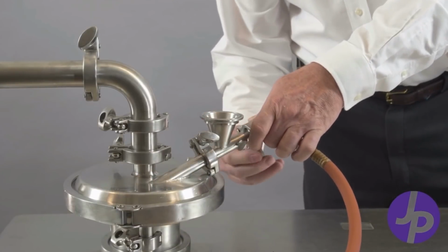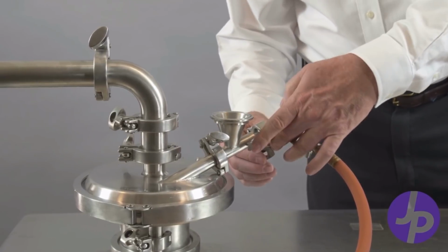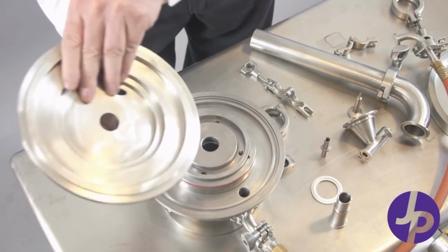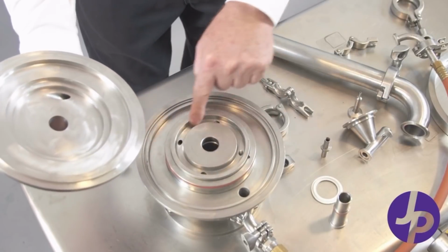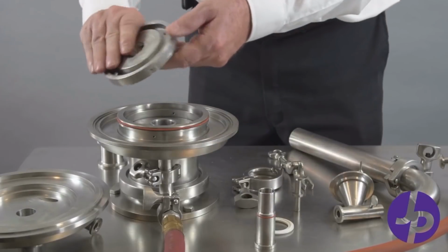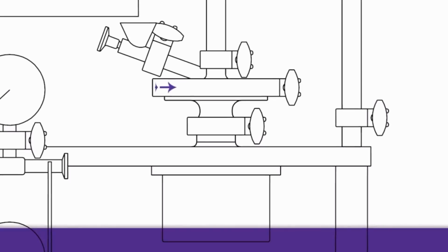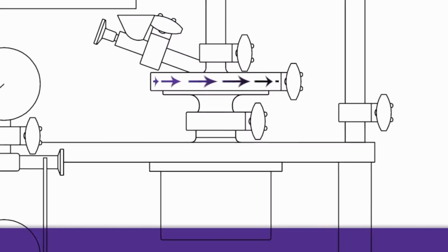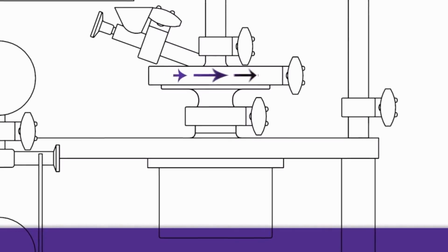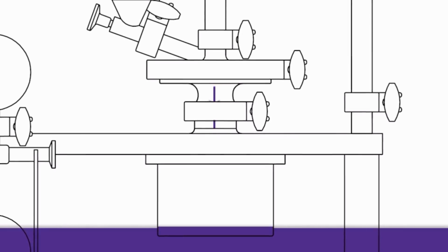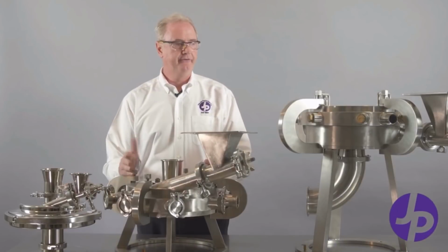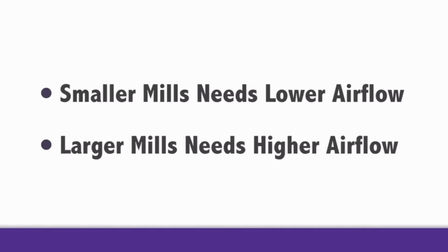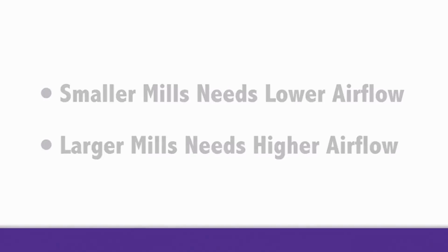So the power source can be nitrogen, it can be air, it can be carbon dioxide. The material is injected into the jet mill. In our case, it goes into the first chamber, which is a distribution chamber. It is evenly distributed and goes through multiple ports in front of the grinding jets. The material goes to the grinding chamber, it goes out into orbit. It stays in orbit and collides with other particles of the same material. As soon as they're fine enough, they migrate towards the center of the mill, climb over a weir, and they're air classified as they come out. Each mill requires a different flow of motive gas. The smaller the mill, the smaller the airflow. The larger the mill, the higher the airflow and the higher the throughput.